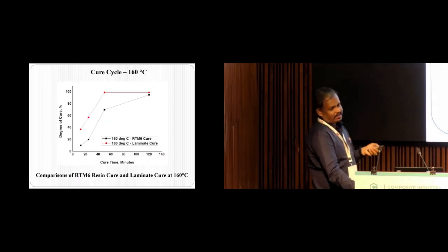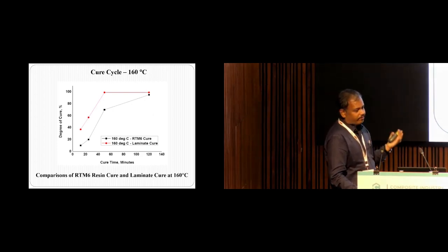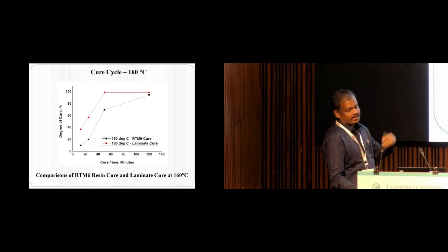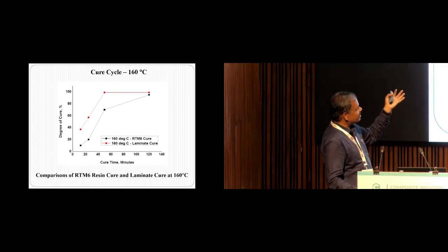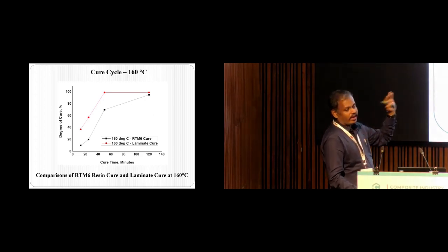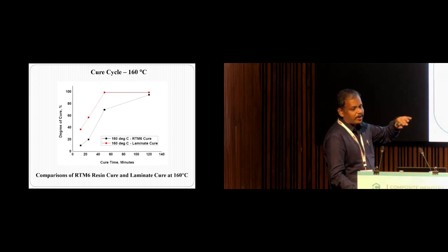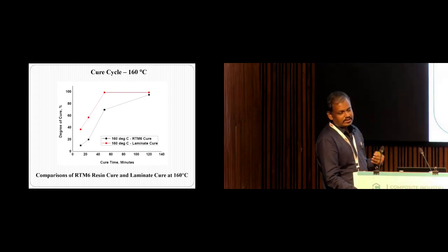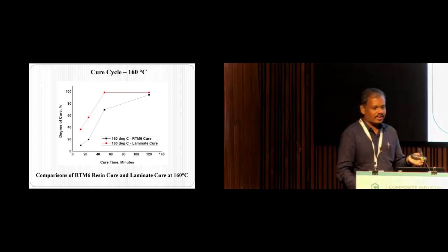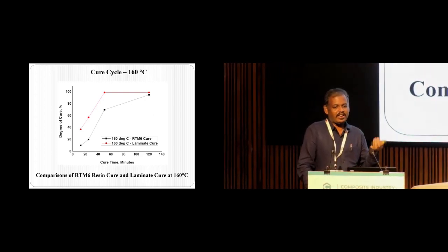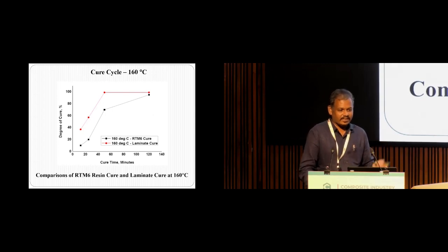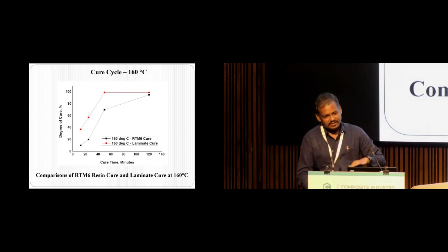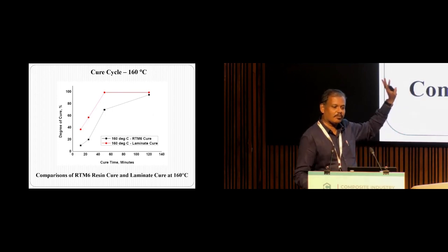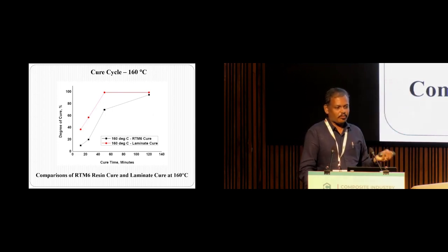If you compare the cure evolution behavior of the RTM6 resin and the laminate, you can see that the resin cure is lower compared to the composite laminate. Earlier I said that carbon fiber can give some resistance to heat transfer, and it is expected that the degree of cure should be lower than that of the resin, but in compression molding it is just the opposite. So what may be the reason?